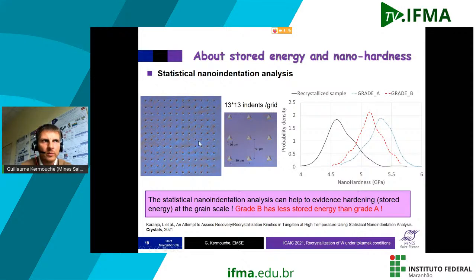So we can perform hardness measurement at the scale of grain. And so we can make a lot of indents on a given microstructure and then plot the hardness distribution. You can see here the results for the recrystallized sample. That means that the sample is fully recrystallized. You have this distribution of hardness that corresponds finally to the different orientations in the material.